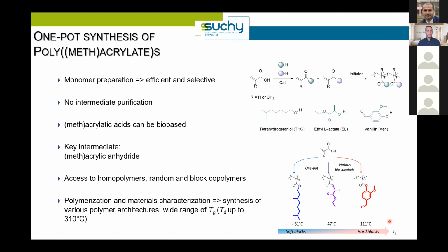And in all cases, we were able to obtain copolymers with a very high Tg by using vanillin as a comonomer. So we believe that this kind of polymethacrylates could have a great potential.